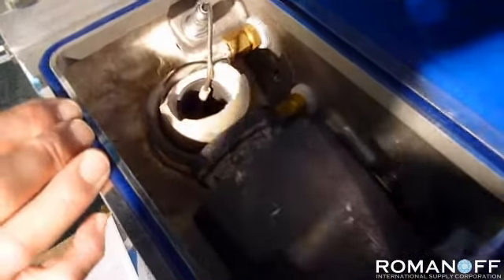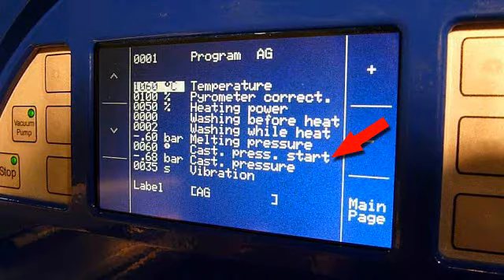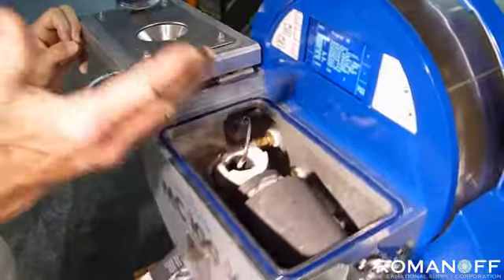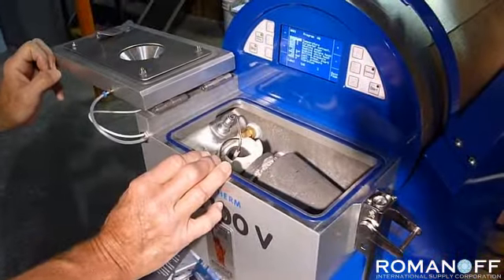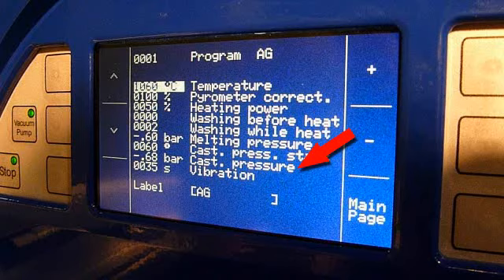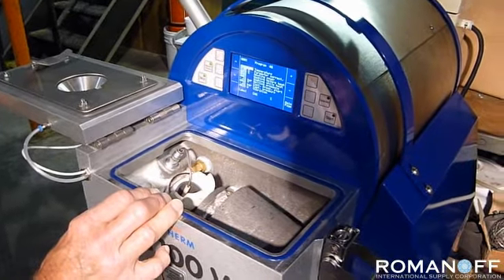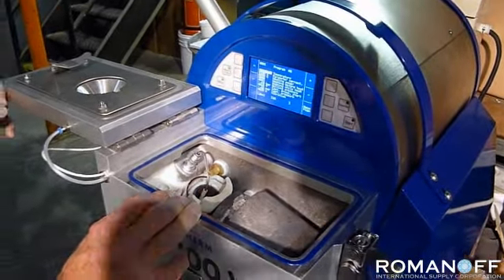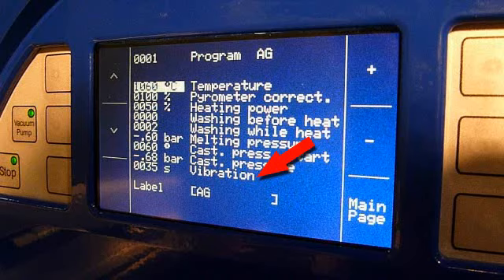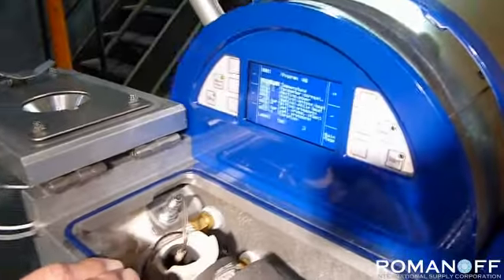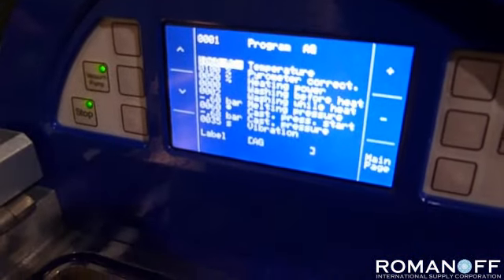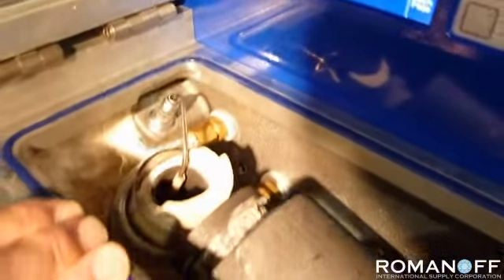The next parameter is when the casting pressure will start. That would be the point at which the casting chamber is tilted and the pressure begins. The next is the amount of pressure that you want to put on the casting chamber, up to a maximum of 2 bars of pressure. And the last parameter that you can select is the amount of time of vibration. The vibration helps the metal solidify into a very dense mass while it is solidifying. Generally 35 or 40 seconds is sufficient to accomplish the purpose.